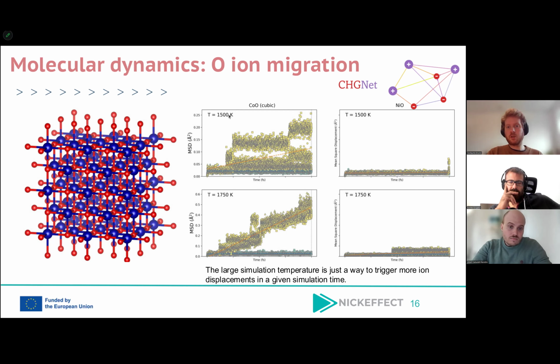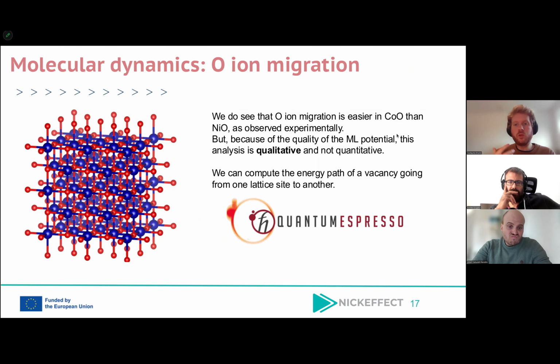When you increase the simulation temperature, then you see that in cobalt oxide, the oxygen atoms indeed start to move, while in nickel oxide, they are not moving at all. And so we do see that the oxygen ion migration is easier in cobalt oxide than in nickel oxide. This is what was observed experimentally. So that's good. But this is still a qualitative analysis. It's not fully quantitative because it depends on the quality of the machine learning potential. And CHGNet was and is still a good tool, but it's not leading to fully quantitative results in the end.